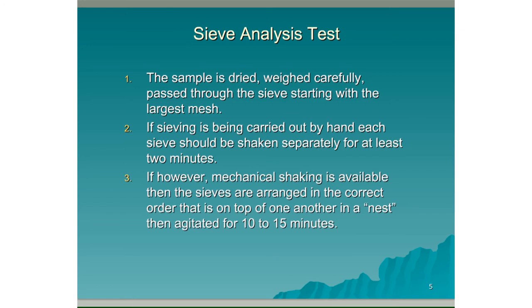If however mechanical shaking is available, then the sieves are arranged in the correct order — that is, on top of one another in a nest — then agitated or shaken and vibrated for 10 to 15 minutes.